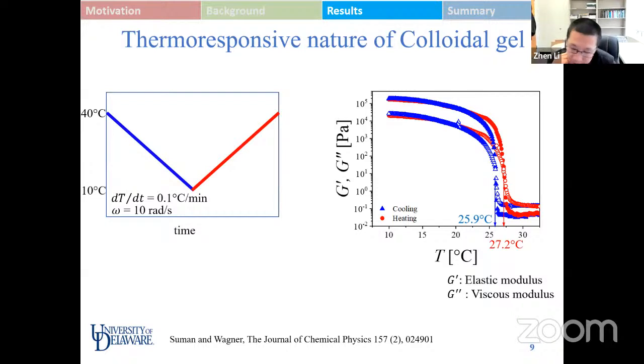Okay. Another question related to this kind of rheology behavior is, have you tried to change the coating thickness, because you need to stabilize the system. Usually you use a 1 or 2 nanometer surface coating. Have you tried to change it? For example, I make the thickness bigger. Will the thickness of the surface coating significantly change the rheology behavior of the system?